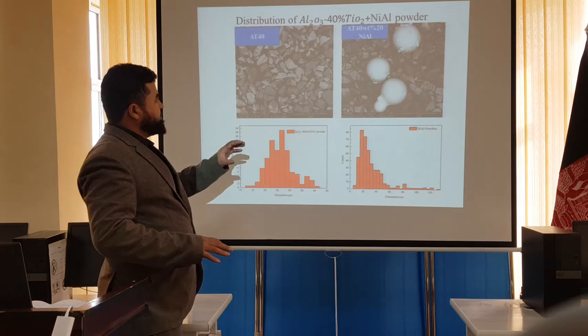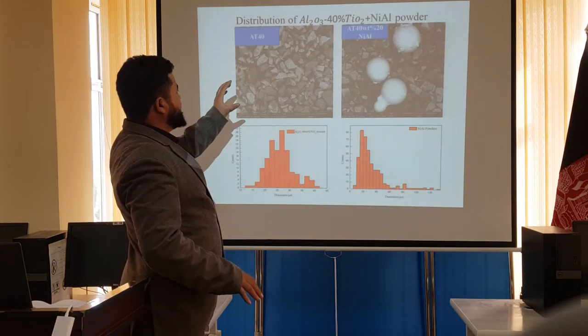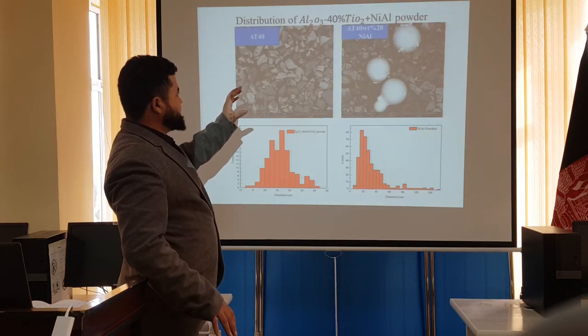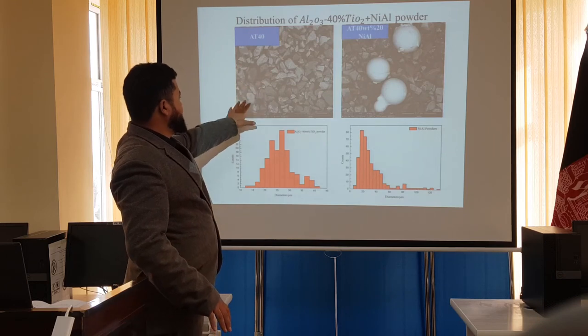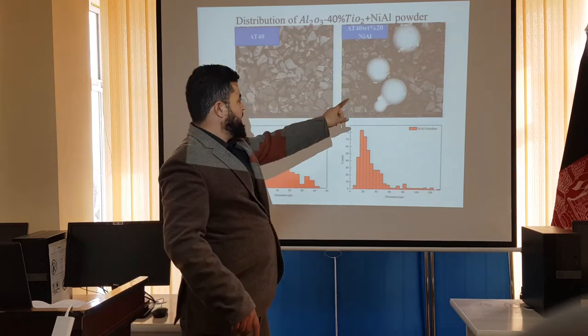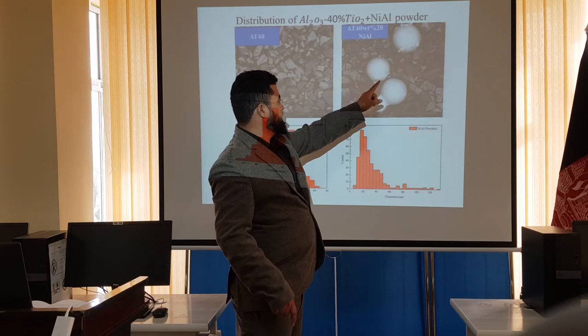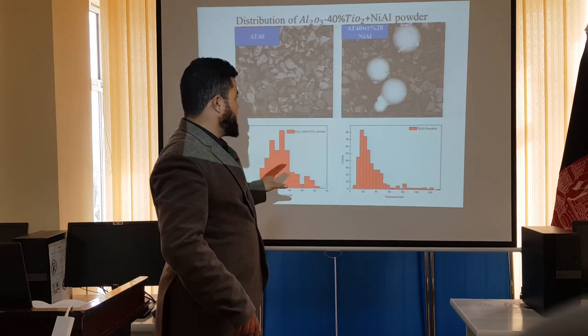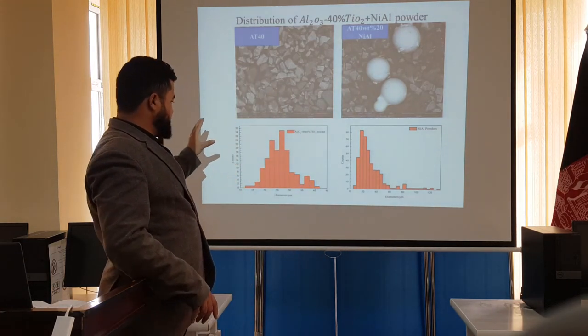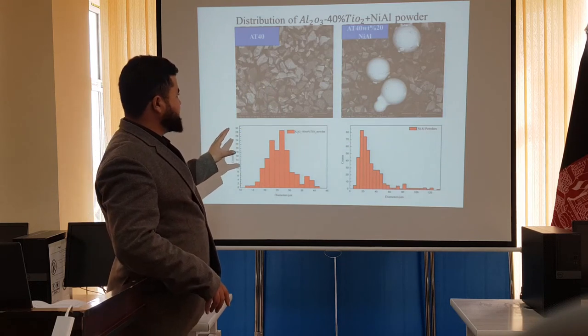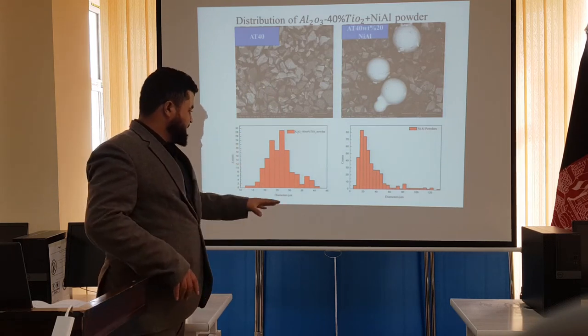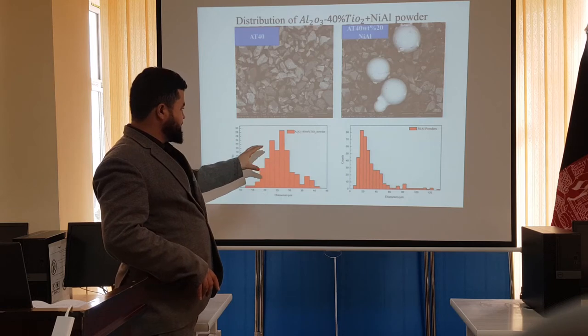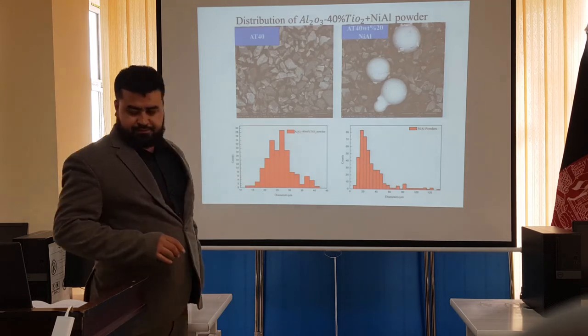This is the composition of the powder, the distribution of AT40 plus nickel aluminum powder. Here is pure AT40. Here we use nickel aluminum base alloy and this AT40 powder. We took a picture by SEM after doping. And here is also the macro size of the composition of our powder.